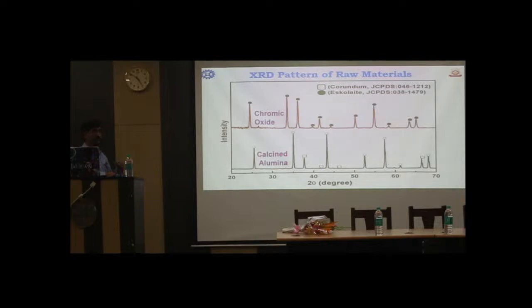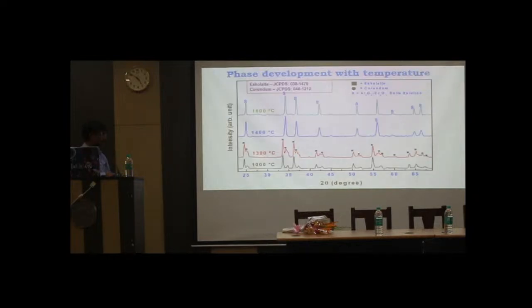Now, in one case we mix a 1:1 molar ratio, 1 alumina, 1 Cr2O3. Then if you heat it at different temperatures, even at 1000 degrees centigrade or 1300 degrees centigrade, you see both phases: this one is the corundum, this one is the eskolaite, the Cr2O3 phase. So both phases are present, that's why there are two peaks at a particular angle.